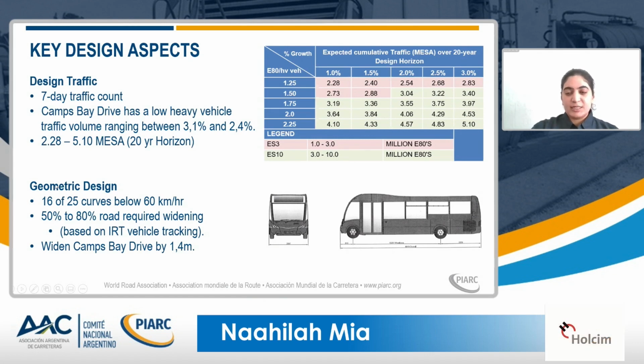The geometric design, as I mentioned earlier, there is 16 of the 25 curves that were below the 60 kilometer standard, and 50 to 80% of this road then required widening due to the buses that will be using this road. So it was then concluded that we will widen this road by 1.4 meters.